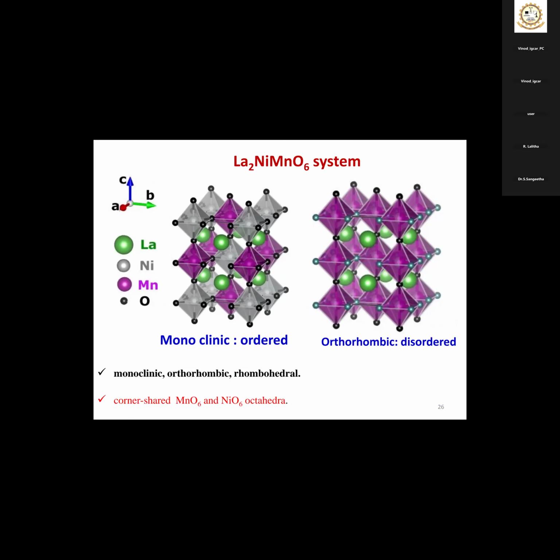The other possibility is that it is disordered. That means manganese and nickel are not perfectly ordered; manganese and nickel sites are randomly distributed. See, on the left, each manganese will be surrounded, after oxygen, by nickel neighbors. That means the neighbor of manganese will be nickel. It's perfectly ordered. That will form a monoclinic structure. And the other possibility is orthorhombic.